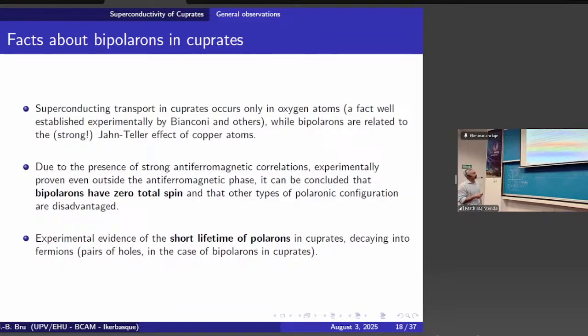And one thing that I did not say in that slide is that there is experimental evidence of a short lifetime of polarons. If you were trapped and stayed forever, then nobody would participate in the transport. But the point is these polarons do not have a long lifetime. So sometimes you are trapped, you make a bipolaron, but then you are released. So this is experimentally shown, that they have a short lifetime.